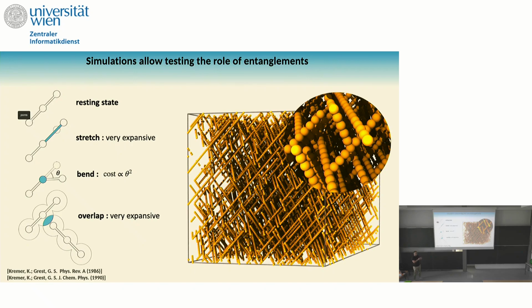If I move the particles together and stretch these links, this is very costly, very expensive. I have some bending rigidity. I have a filament with some bending rigidity. If I bend it, it costs energetically, and the cost is proportional to the angle that I will form, or the deflection. And also they cannot interpenetrate. If I have two filaments that come together, then I put a repulsive force between them, and then they will not interpenetrate. This is a video or a picture from experiment. You see that you have these branches that we designed, made by several particles that are attached together.